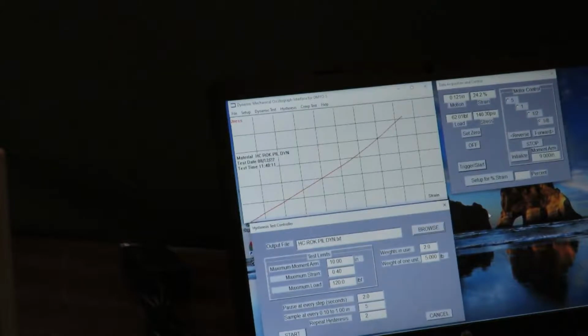What's important in hysteresis is loss of energy. As the specimen experiences compression forces, when the forces are reversed, some of the energy is wasted in the viscous component, and the elastic component, of course, stays the same. However, it depends on the filler structure, the agglomerate, mixing, cross-linking structure of the final component, and how it behaves once it comes out of a mold.